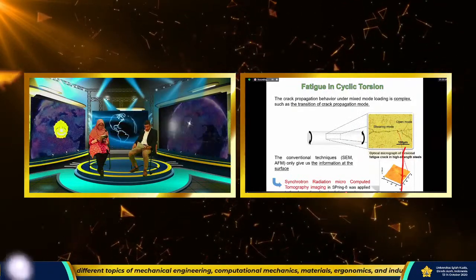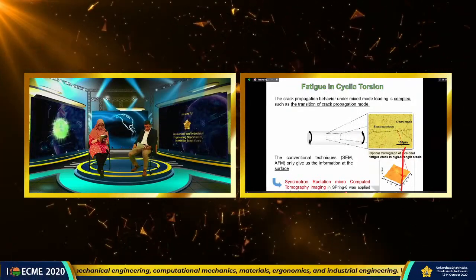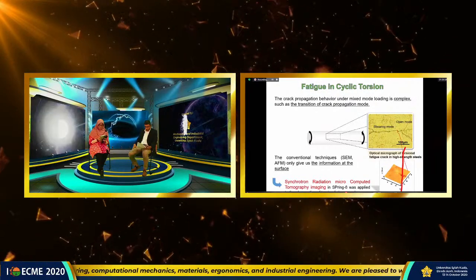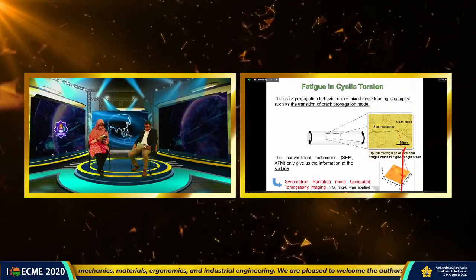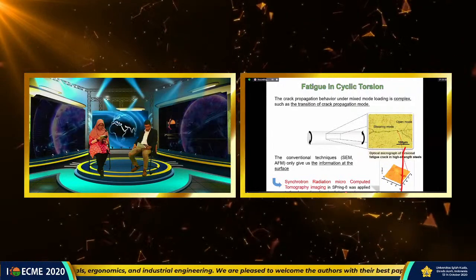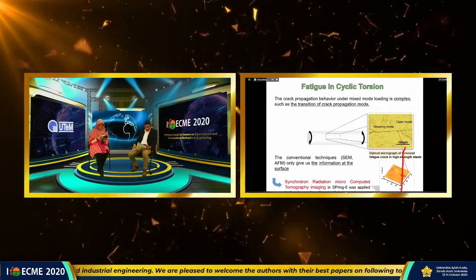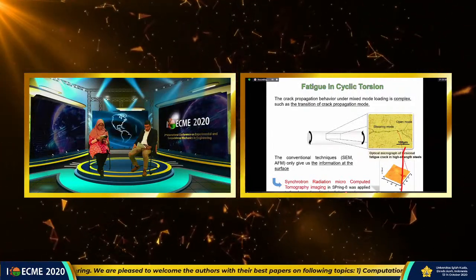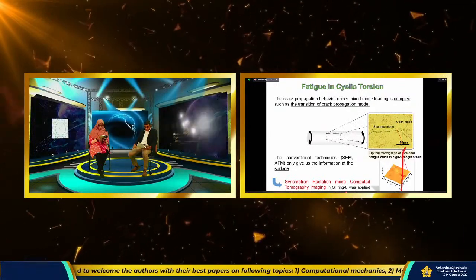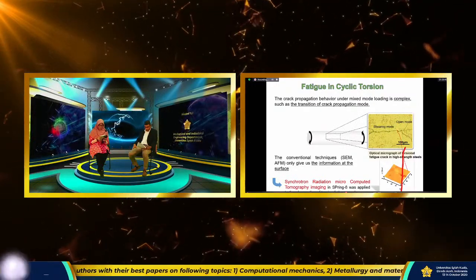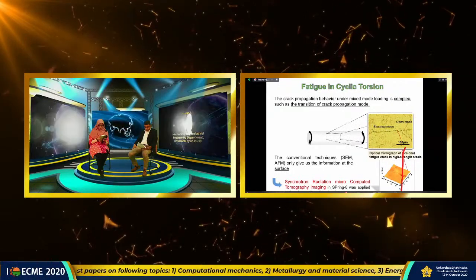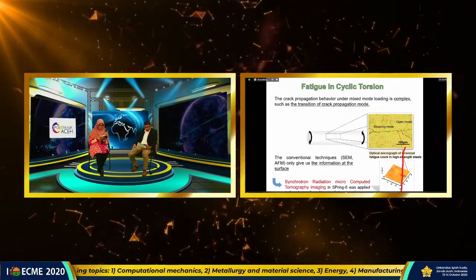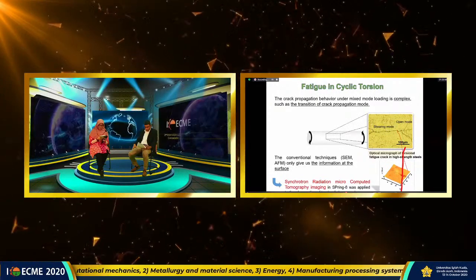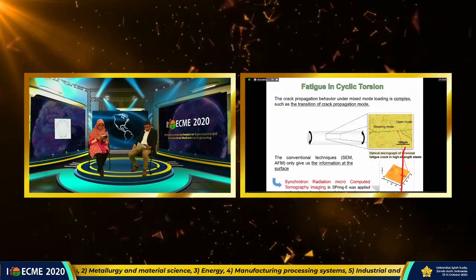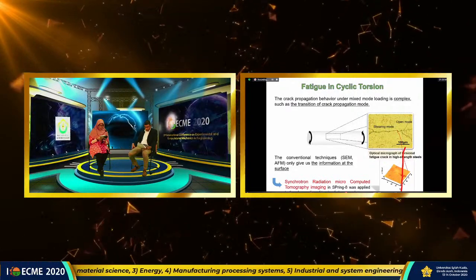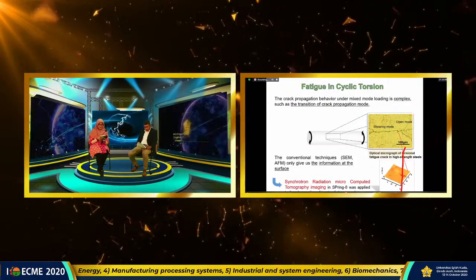As you know, crack propagation behavior under mixed mode loading has been studied for a long time. The crack propagation behavior is very complex, including the transition of crack propagation mode. The transition condition must be controlled by a fracture mechanics parameter, such as stress intensity factor, but for surface cracks, it cannot be calculated without measuring the 3D shape of cracks.